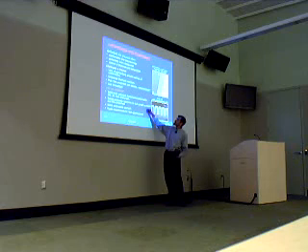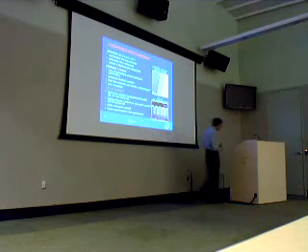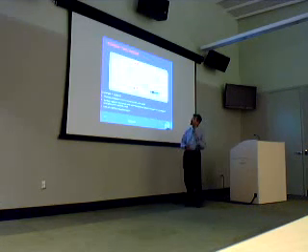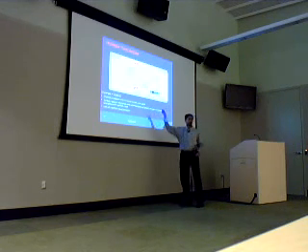Some of the key things is this is aluminum oxide, a high K dielectric. And the reason we have to use modeling is for new gases and new precursors, they did not know a lot of the properties. And some of them were toxic, so you could not do experiments in a detailed manner. Well, in simulations, of course, we have the luxury of not getting the toxicity part of it. And then it could guide the experiments for ALD optimization. But the problem in ALD is not just the rate kinetics alone. You also need to be able to look at these multiple time scales. You have the gas flow into the growth regime.